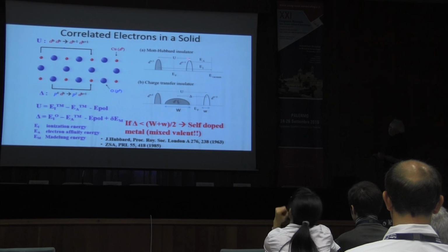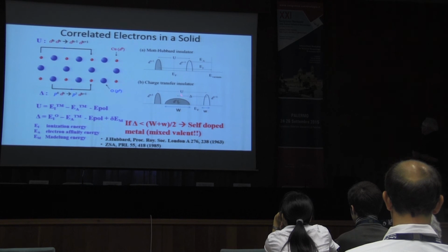The gap here between removal and electron addition would be U. But you can have the oxygen bands in between here, and if the charge transfer energy is less than this Hubbard U, then in fact the lowest energy excitations are charge transfer excitations. And in fact, if you dope this system with holes, the holes will not go into a d band, but will go into an oxygen p band. Those are called charge transfer gap systems. Now, if this charge transfer energy is so small that this overlaps with that, then we have a system where you really get complicated, and those are most of our systems, actually, that are really interesting.